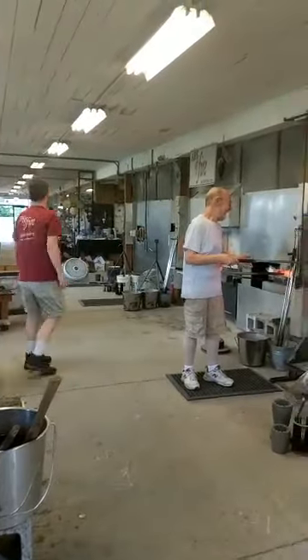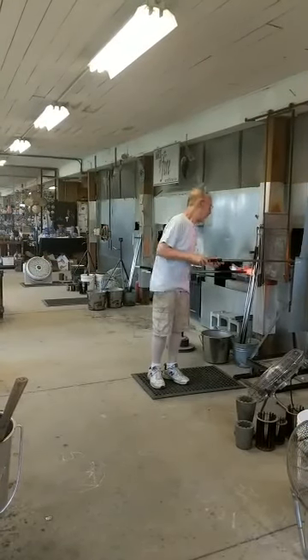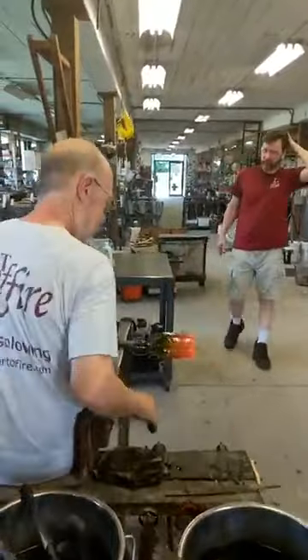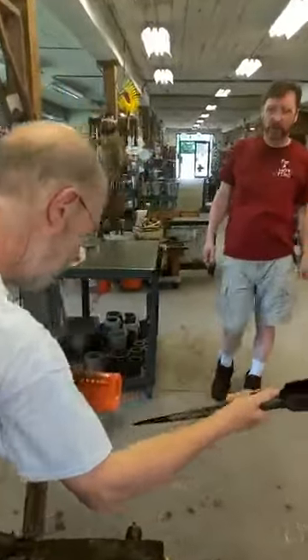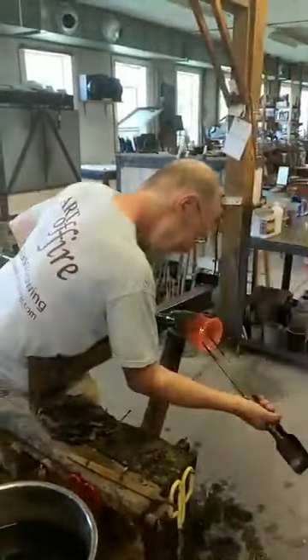So anyway, back to that business of the 900 degree annealer. When we put the glass away in the annealer, the glass might be at 1,300 degrees Fahrenheit. And the glass is really very good to go down to 900 degrees from there and hold. In fact, it can hold there all day, and that's in fact what we do.